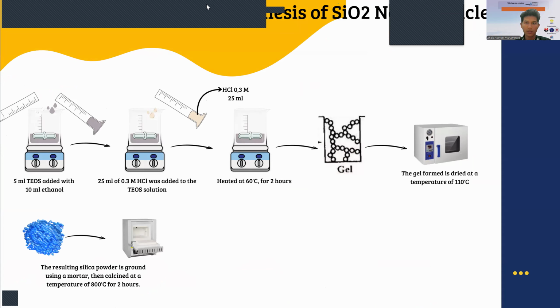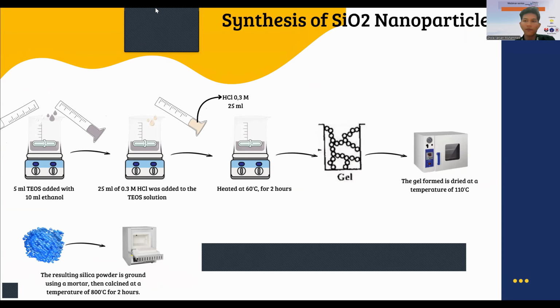Step number one is synthesis of SiO2 nanoparticles. Synthesis of SiO2 nanoparticles using the sol-gel method with TEOS, tetraethyl orthosilicate, precursor. Step one, 5 milliliters of TEOS was added to a 240 milliliter beaker glass, followed by the addition of 10 milliliters of ethanol. The mixture was stirred at 500 RPM for 10 minutes at room temperature.